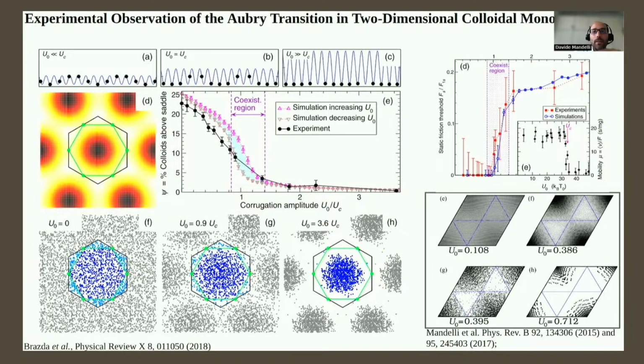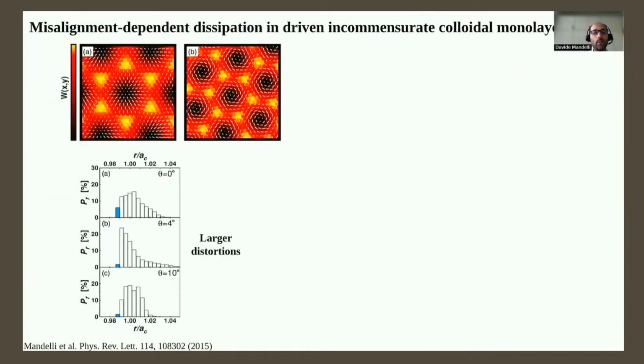I will not go into the details, but a few years after we published our results, the Aubry transition was actually observed for the first time in a two-dimensional colloidal monolayer, showing the same features that we obtained in our simulation. I will now proceed by presenting some results on the dynamical properties of sliding incommensurate colloidal monolayers, and in particular, how we can control friction by controlling these mass density waves, these equilibrium distortions of the fully relaxed static monolayer.